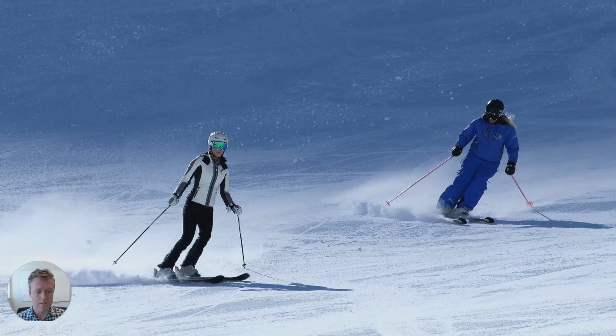If you look at this one right here, we've got downhill skis. These are the longest skis. They're designed for maximum speed and stability. Key features are long length and stiffness. They're very stiff for edge hold at high speeds. They have minimal side cut for stability. Material focus is stiff cores, metal laminates, titanium or aluminum for damping, and torsional rigidity.